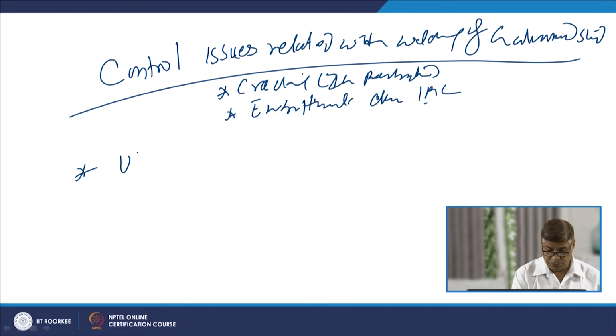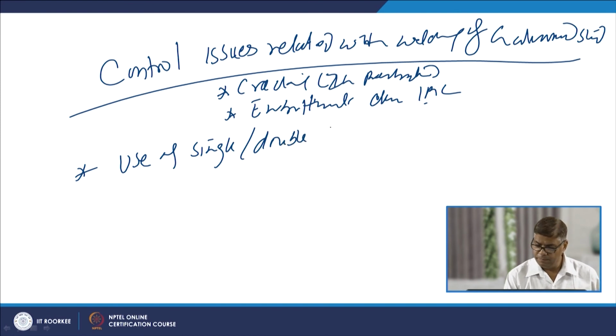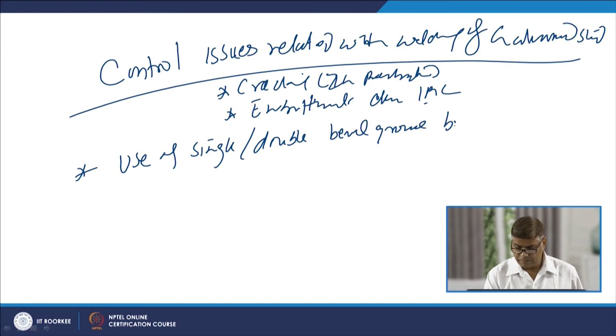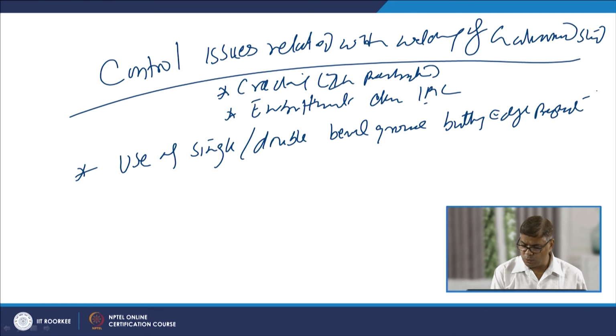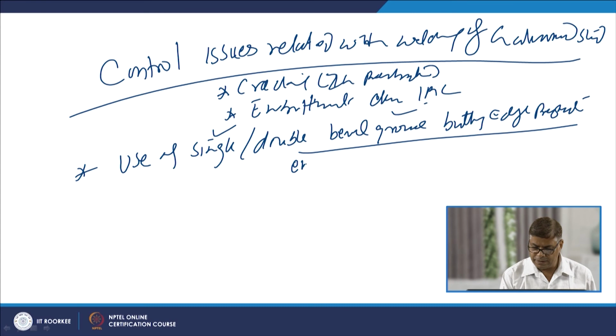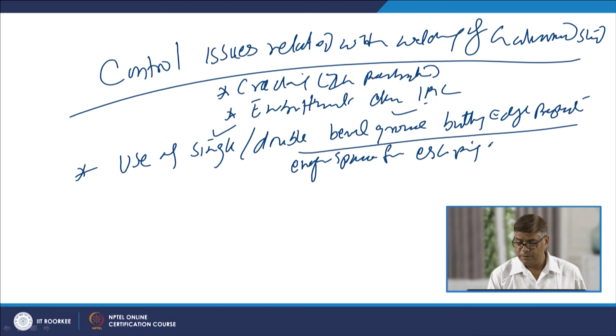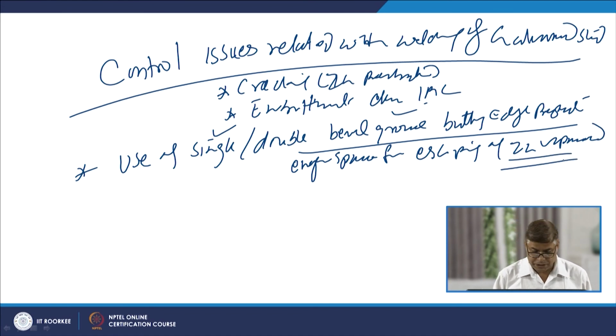One is the use of single or double bevel groove butting edge preparation. Instead of the square one, we prefer to use the single or double bevel groove butting edges, so that it provides enough space for escaping of the zinc vapors which are produced due to the evaporation of the zinc during the welding.